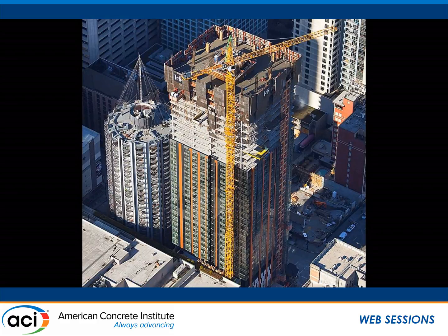What we found on tall buildings in recent years is that most contractors prefer now these very well-engineered Tinker Toy handset systems. This happened to be the Titan system. There are others in the market that are equally good. Cary has a very good one. Meva has a very good one, other companies do as well. But what we found is that for high-rise buildings like Premier on Pine, in recent years, the majority of the contractors we work with actually prefer these handset Tinker Toy engineered systems as opposed to fly forms, which gives us as designers a real advantage because we don't need to worry as much about column alignment.